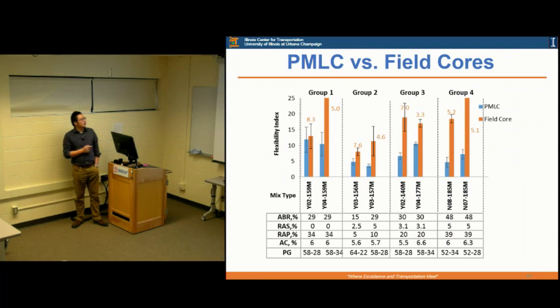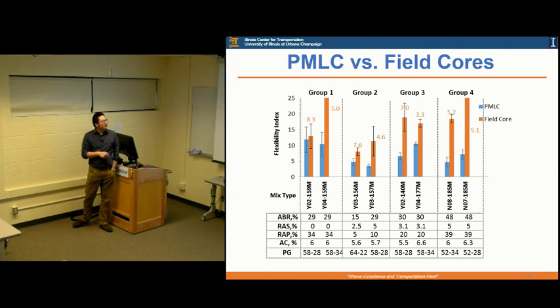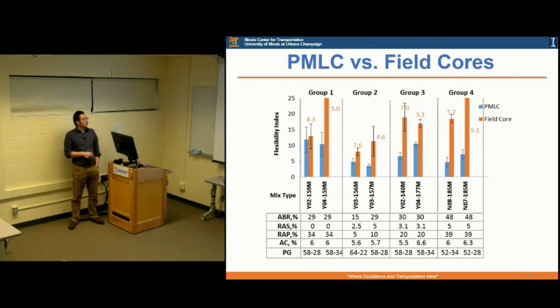This is one of the results from the iFit test. The orange bar is the field core, and the blue one is PMLC, the plant mix laboratory compacted. We all see that general trend that the field core had a higher FI than the lab, which means that in the field, your mixes tend to be softer than the ones we prepared in the lab.